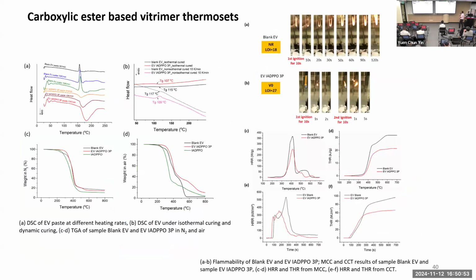Okay, and obviously you can get very high fire performance on the right. You can see you can get a high LOI. You can also get a V0, but you need 3% phosphorus to get this. And in this chemistry, the action is more in the gas phase, where the phosphorus is released in the gas phase, and it quenches the radicals very much. You don't form a lot of char, so it's another kind of chemistry, but it's a carboxyester chemistry.